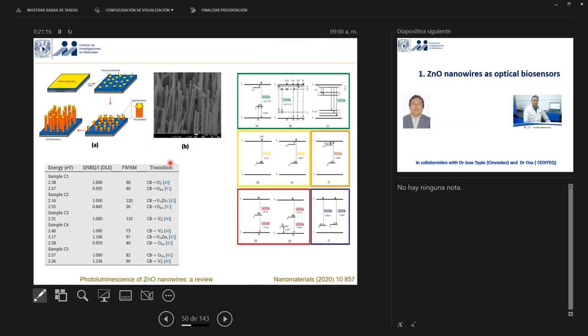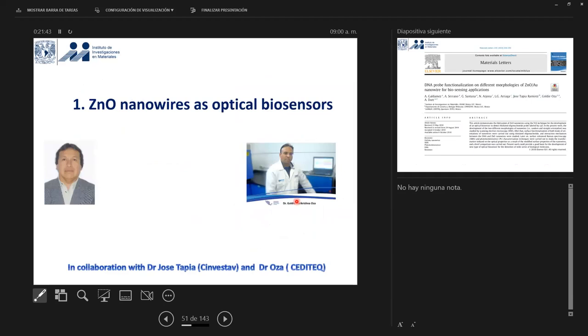There are different kinds of defects that can happen in these kinds of nanostructures. As you can see on the right side, depending on the defect, we can control the band gap, and then we can control the color emission of these nanowires. For example, in the first case they are green, then we have yellow, orange, red, blue. So we can control the defects, we can control the band gap, and then we can control the emission of these nanowires.